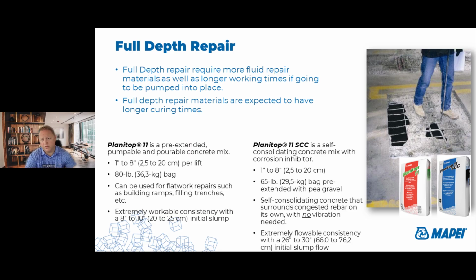Full depth repairs, you're going a little deeper. These are going to have to be a little bit more of a fluid type material. You're going to have a longer working time, but you're also going to have a longer cure time for those. MAPEI has a whole suite of these products. Our Planitop 11, the pre-extended, pumpable, pourable. We have a self-consolidating one. This is nice where you don't need to have a contractor provide vibration to get rid of air pockets in your concrete. It's going to do that. It has superplasticizers mixed in with the mix to do that.